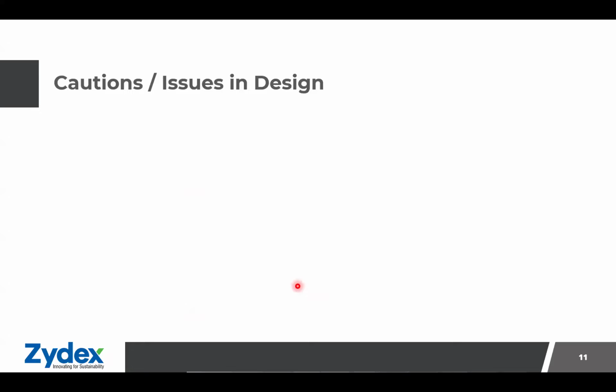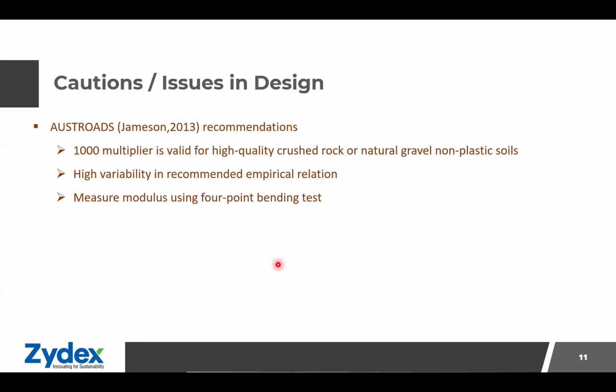Now, I'll be listing out a few of the issues or cautions that one needs to consider while designing the stabilized pavement. The first issue is the empirical equations that we have adopted for the calculation of resilient modulus, that is the multipliers 750 and 1000, are valid for high quality crushed rock or natural or non-plastic soils. Also, the authors recommend that there is a high variability in the empirical equation, and therefore they recommend to measure the modulus using 4-point bending test.